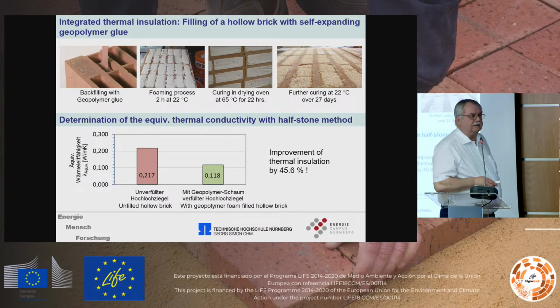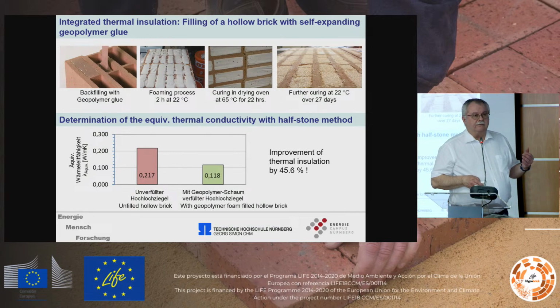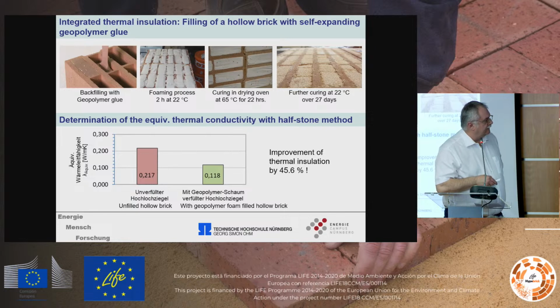We integrated the geopolymer glue in bricks. Here you see a hollow brick, and here we fill the geopolymer glue in this hollow brick, and then you have to wait 2 hours as example, so you see it there. The hollow is filled with geopolymer, and here the structure, you see porous material, and we can give mixed rubble or concrete rubble in this geopolymer foam, and we fill this in the bricks.